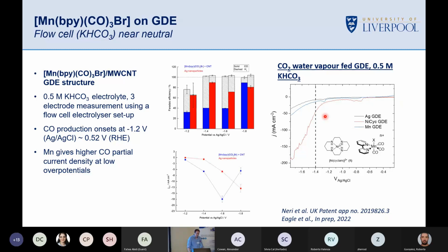And apologies, that's a little small, and the people in this room can't even read that because it's pixelated. But if you're online, you can probably see that this shows the silver in red, the manganese catalyst in blue, and the solid blocks are carbon monoxide, the dashed blocks are hydrogen. So you can see that the Faradaic efficiencies are repeatedly better for our silver electrode, but because we've got a higher current density, our partial current density for our manganese electrode is significantly better. So we're pretty pleased with this.